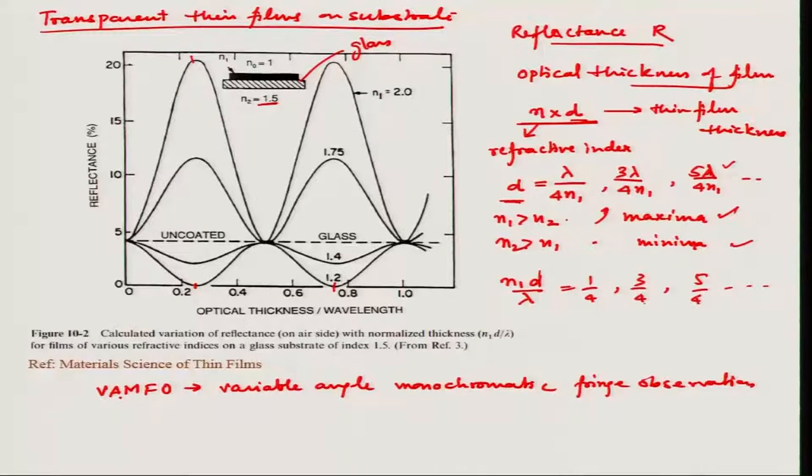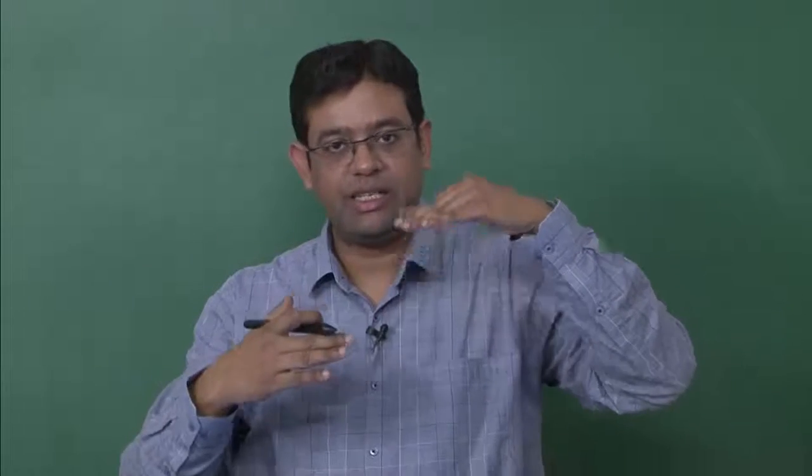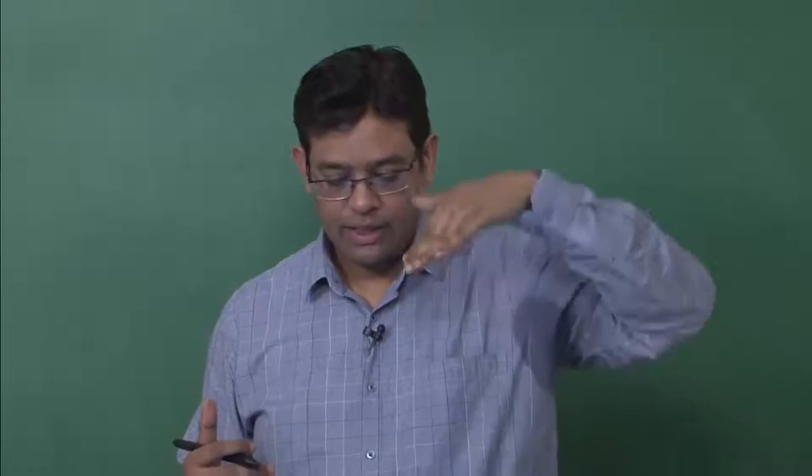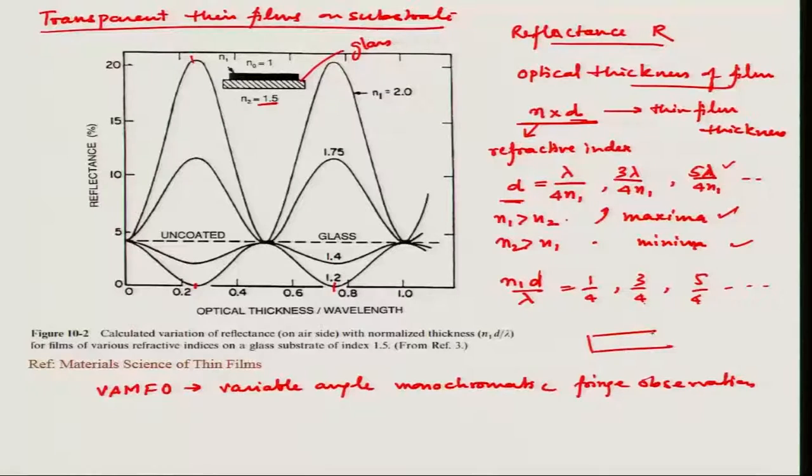Now, in this method, your lambda is fixed, you change the angle of the light which is falling onto this. When you change the angle, you are changing the optical thickness, because the distance the light travels in your film is changing, right? So if you are changing this angle, the distance it travels inside the film is going to change. From this you can observe different peaks by changing the angle,